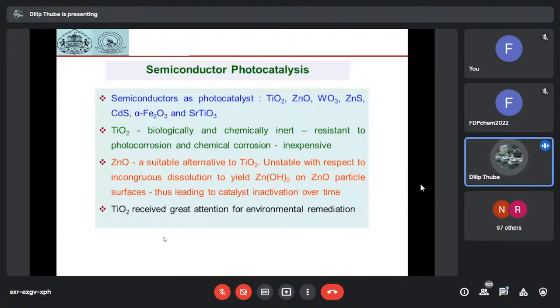So the cost of process becomes very less. Another inexpensive photocatalyst is zinc oxide, which is a suitable alternative to TiO2. But the most important drawback is that it is unstable with respect to the incongruous dissolution to yield zinc hydroxide. Whenever zinc oxide particles are used, the zinc hydroxide is formed.